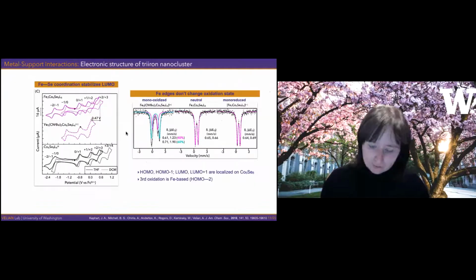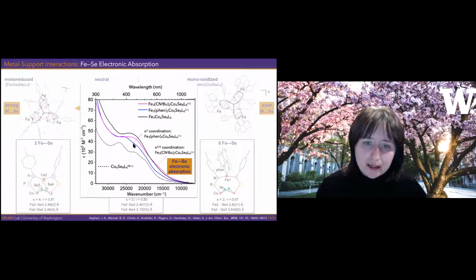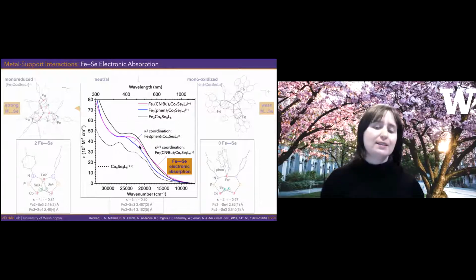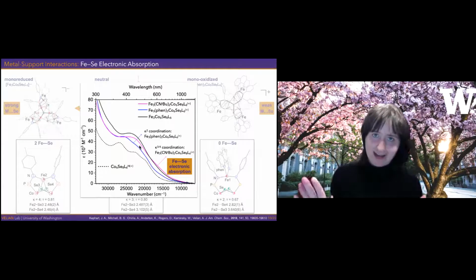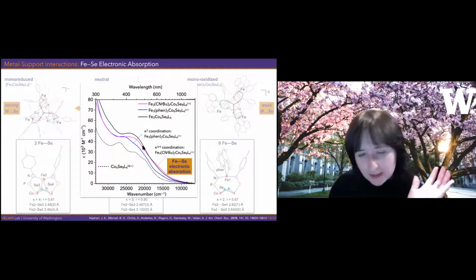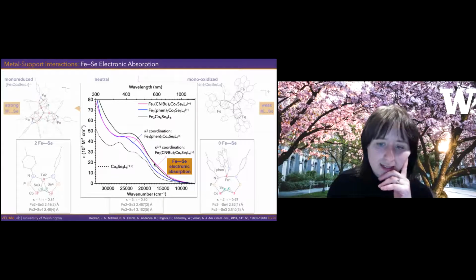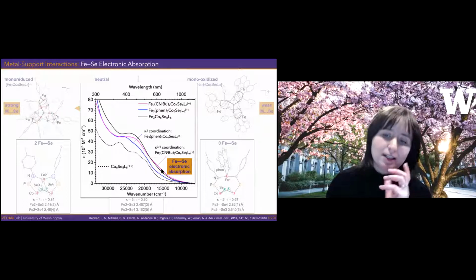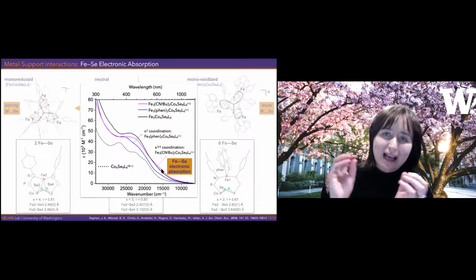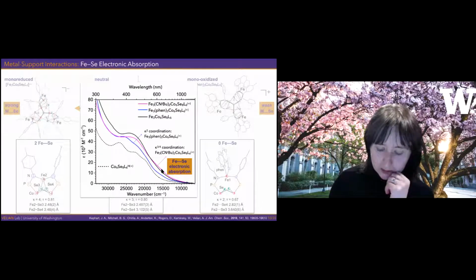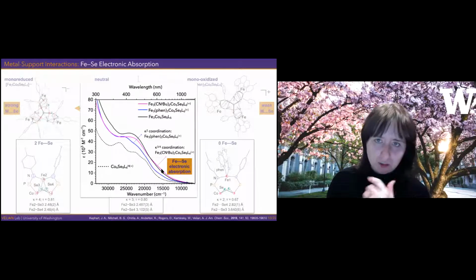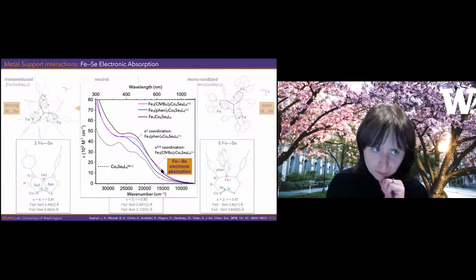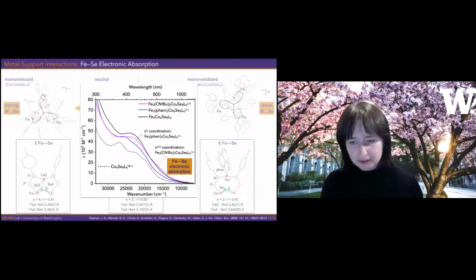But then in pink and in blue, what I'm showing is the difference between having those iron-selenium interactions or not having them. Obviously there are other things going on here, but we think that this red shift going from blue to pink is associated with having these iron-selenium interactions. And it's kind of cool to see that they're associated with an absorption at such low energies, even if it's really hard to interpret because it's not a nice Gaussian.